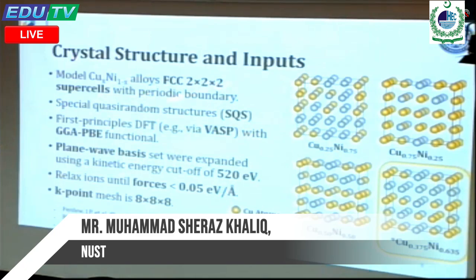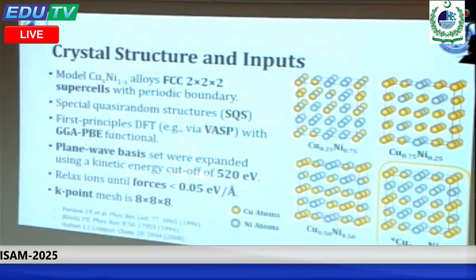And these are the setups. First, FCC 2x2x2 supercells with periodic boundaries and special quasi-random structures, which naturally model the randomness of atoms in a crystal. Then we apply first-principles DFT from VASP, the Vienna Ab initio Simulation Package, with the generalized gradient approximation and PBE functional. Plane wave basis sets were expanded using a kinetic energy cutoff of 520 eV, which means that any electron with energy less than 520 electron volts will be simulated.